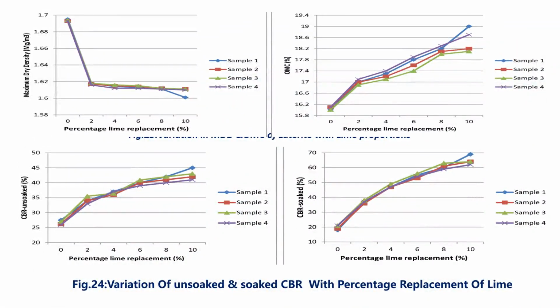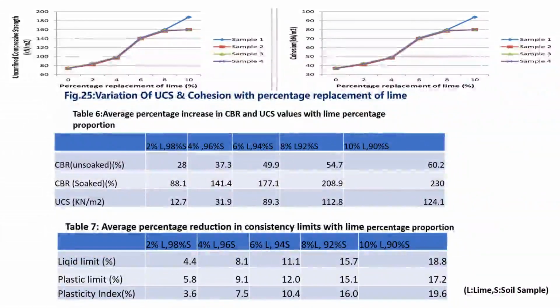Now, the unconfined compressive strength and cohesion also increase with increase in lime content in percentages of 2, 4, 6, 8, and 10%. From the table, the average percentage increase in CBR and unconfined compressive strength are shown and indicated. Also, the average percentage reduction in consistency limits with lime percentage proportion are indicated in the table.